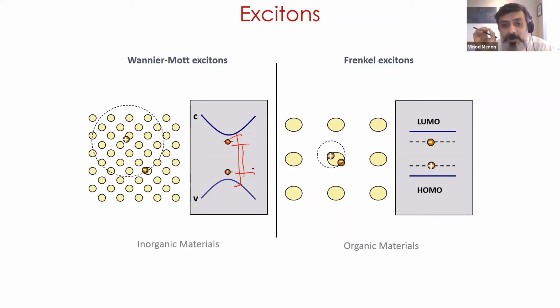In the case of organic molecular systems, the excitons are different in the sense that the electron and the hole are actually sitting at the same molecular site. So they're very tightly bound. And because they're tightly bound, they have a large oscillator strength typically. They're also shown by these energy levels which sit below the band gap.